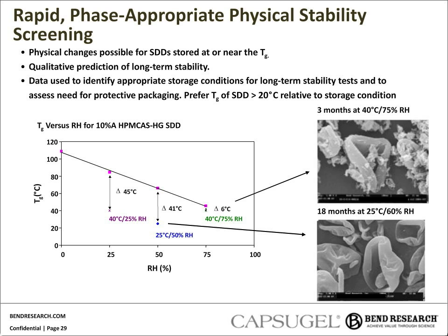And what we look at is that delta between the storage condition and the glass transition temperature, and use that to guide whether or not we think a formulation has the potential to have some physical stability issues at a given condition. So in this example, what we're showing is that when the TG is 40 degrees higher than the storage condition, here we show with this SEM, no crystals are growing anywhere after 18 months of that condition. Whereas when the TG is less than 10 degrees from the storage condition, even after 3 months, we're starting to see crystal growth. So that's the way that you can use this type of analysis as a guide.